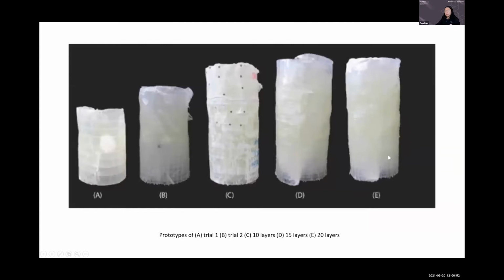And we also test different FRP layers. So this is an experiment with different trials of failure and success. We have found, just based on experiment, that between 15 layers and 20 layers is the minimum amount of layers to support the system, based on the epoxy resins that we're currently using.